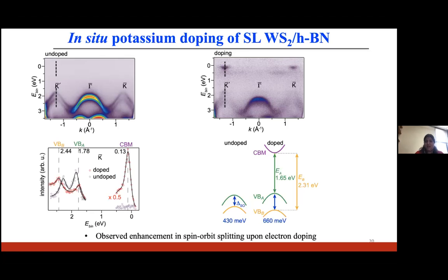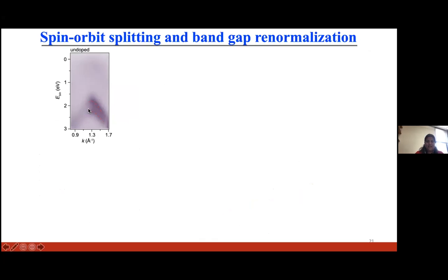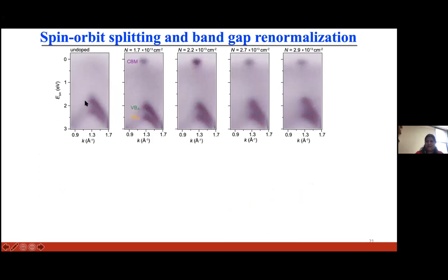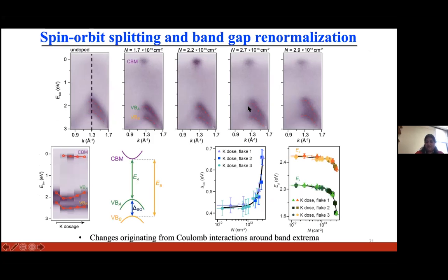Next, I'm going to look at what's happening at the K point in much more detail. Once again, this is for the undoped sample, and here I am showing it as a function of dosage. You can see we are increasing the dosage. At the K point, we can look at the features much more clearly if we take the line cut for the undoped sample and at each of these dosages. Again, I'm plotting the binding energies as a function of the potassium dosage.